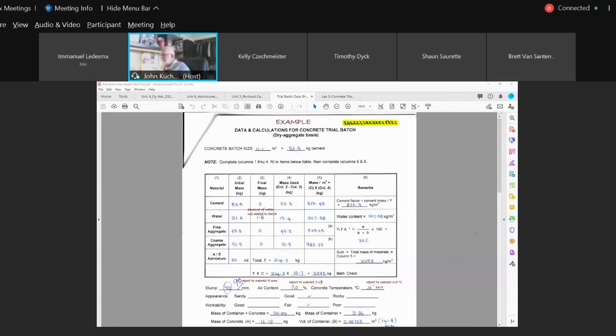But the slump test is a test for consistency. That's why you are determining one batch versus the other batch. You got mix design A. Load 1 comes in, has a 75 millimeter slump. Load 2 comes in, has 75 millimeter slump. Load 3 and load 4 and load 5 and load 6, they all have 75 millimeter slump. That's consistent. That tells you that batching is consistent. The ingredients, the mix design has to be consistent.